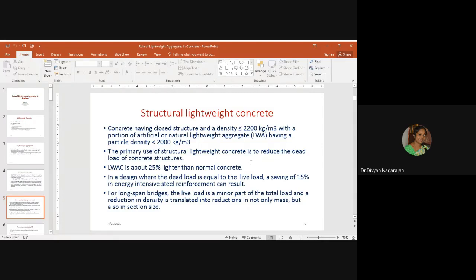The primary use of structural lightweight concrete is to reduce the dead load of the structure. Normally, it is the coarse fraction of the aggregate that is exchanged by the lightweight aggregate. A further reduction in density can be achieved by replacing the sand fraction with a lightweight sand if it is available locally. The primary use of structural lightweight concrete is also to allow the structural designer to reduce the size of beams, columns, and other load-bearing elements. The use of lightweight aggregate concrete instead of normal weight concrete reduces the relative cost, and potential savings can also occur.